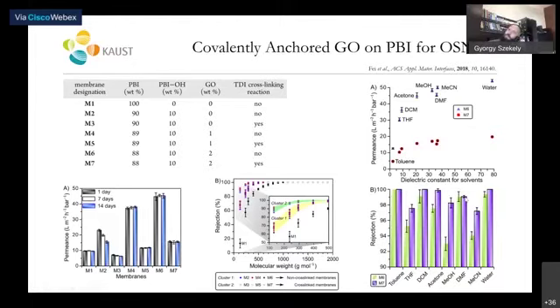So here, what we assume happened is that the GO itself cross-linked the polymer network. So we know that graphene oxide has epoxide groups, and they are highly reactive. So what we assume happened is that the epoxide group reacted with the amine group of the PBI, and to a certain extent cross-linked the network. And this is why the membrane became stable in DMF.